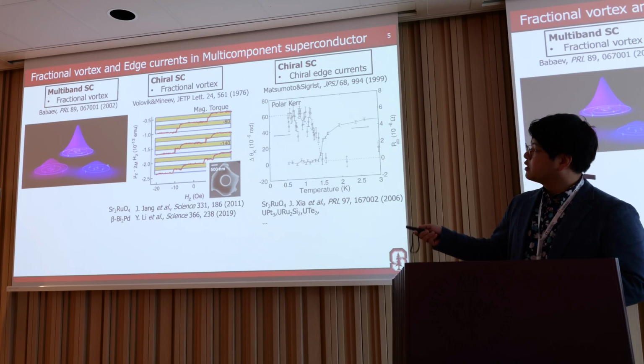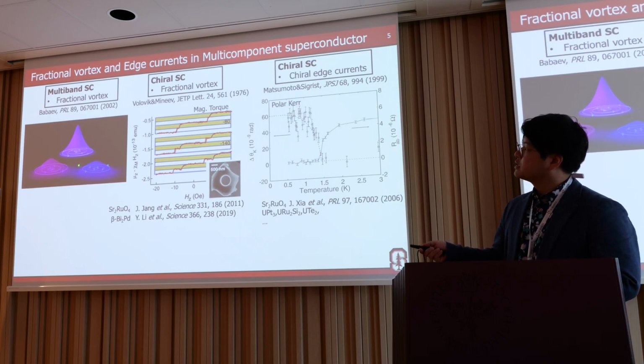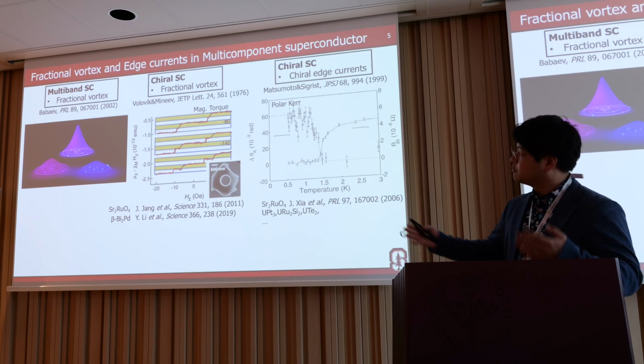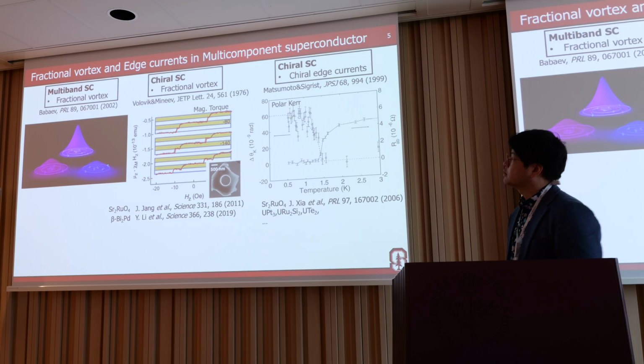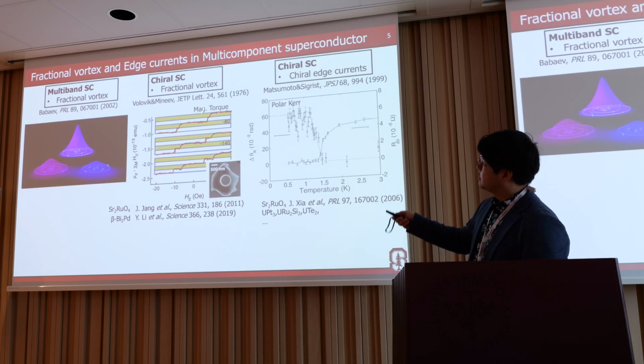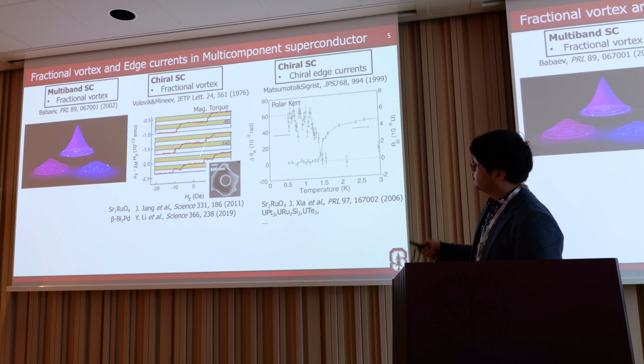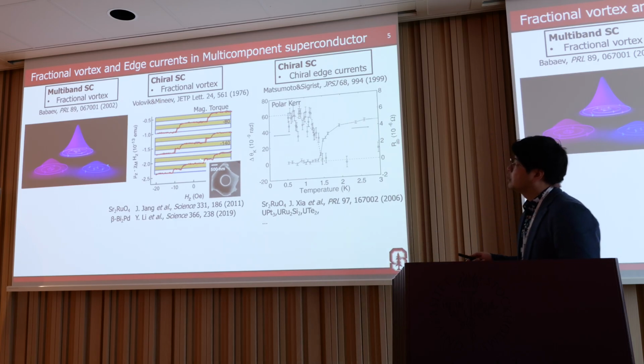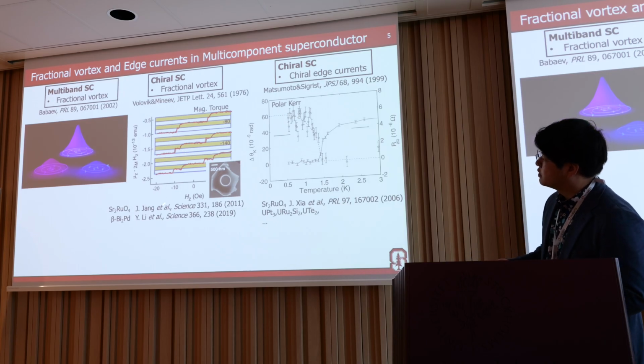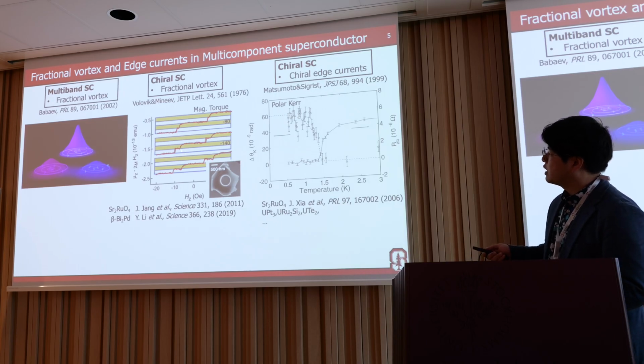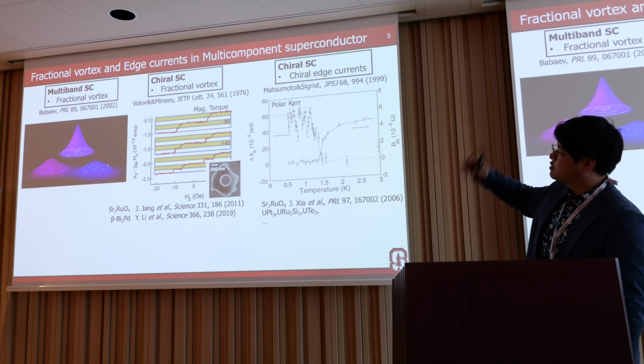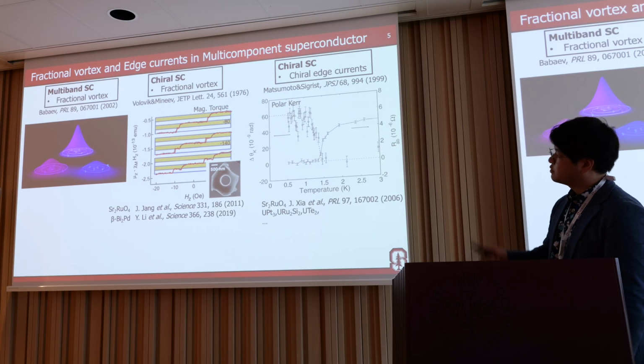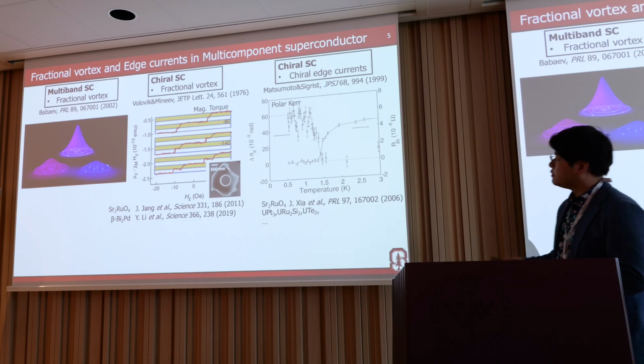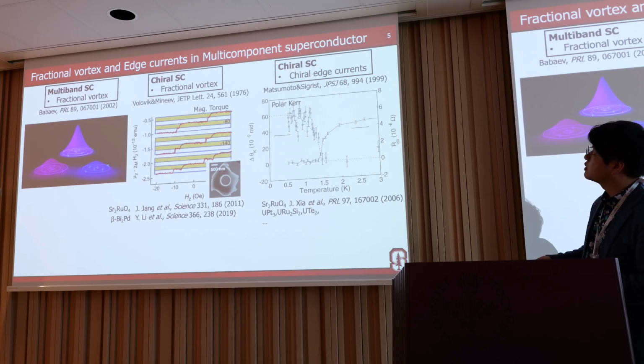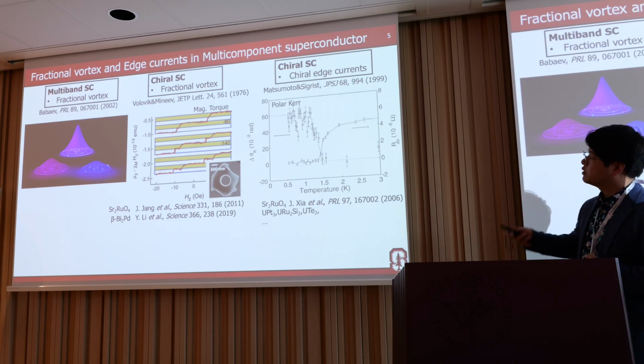As Igor said this morning, his theory predicts fractional vortices in the general multiband superconductor, the bulk superconductor, and the same analogy with the chiral superfluid. The chiral p-wave, spin-triplet superconductor predicts fractional vortices. There is an indirect measurement in strontium ruthenate, where the cantilever measurement shows a half height jump in the magnetization in ring shapes, but there's no real observation of the fractional vortices in real space measurement. And for chiral superconductors, they also expect chiral edge current. I will talk more later.